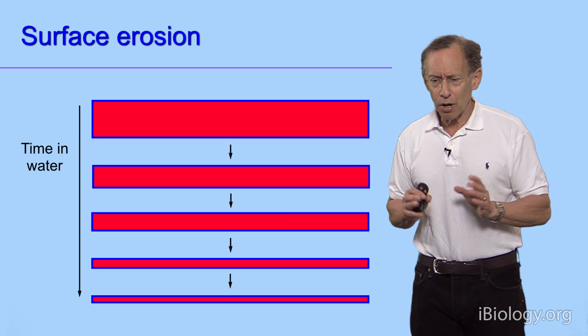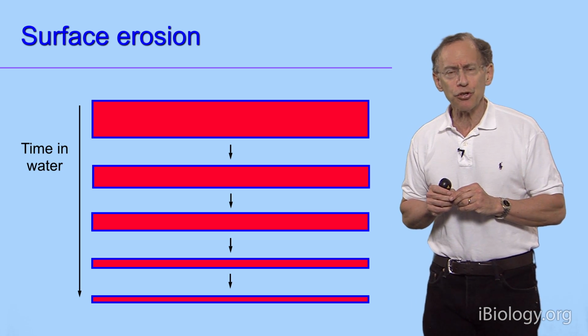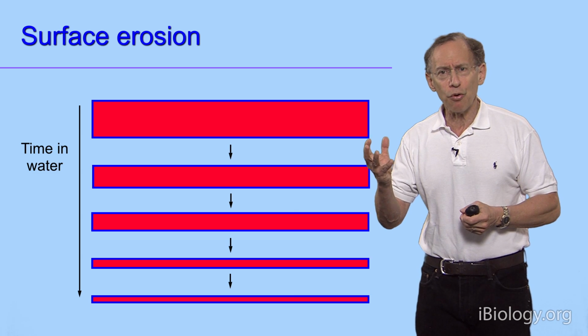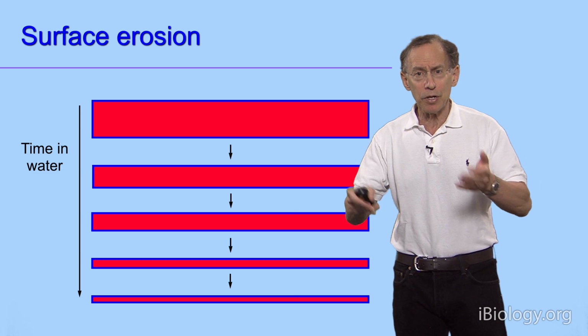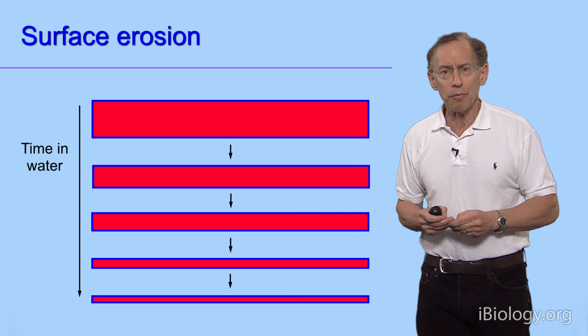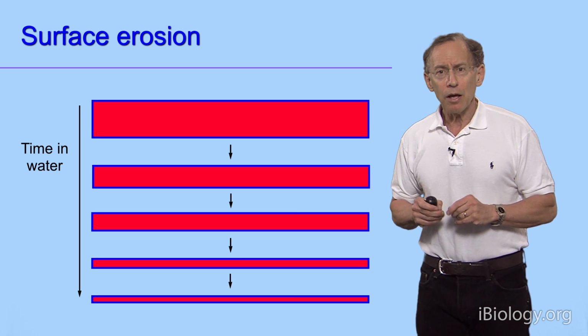So we went through a very detailed engineering design analysis to try to figure that out. We'd start out with different design questions, like what should cause the polymer degradation? Should it be enzymes? Should it be water or something else? Our thinking is, well, everybody may have different enzyme levels, but everybody has excess water. So let's build into the polymer the ability to be degraded by water as a first step.